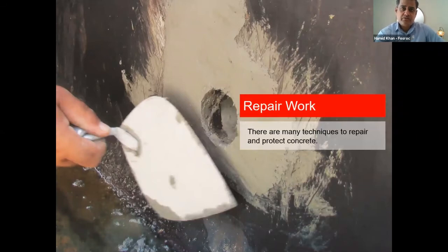So we talked about the repair mortar specification. We talked about the long-term integrity, low permeability, and compatibility. These are very important parameters for any repair mortar. It's not the strength only. As I said, by specifying not only the strength, but also low shrinkage, low permeability, and compatibility, we ensure that the repaired areas are durable.